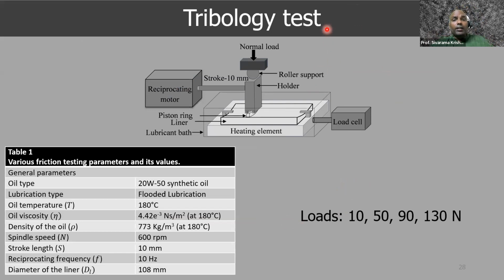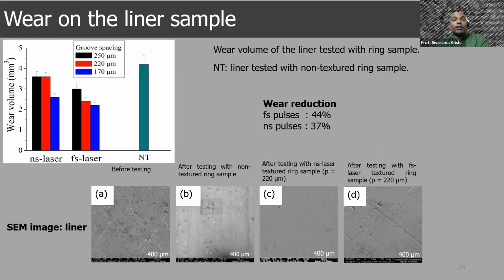So we used a reciprocating motor to measure the tribological properties at various different loads, all the way from 10 to 130 Newton. We used the same oil in both cases, for nanosecond as well as femtosecond laser pulse grooved or microstructured samples, and we studied the tribological properties. That's the work of Maran. And here is a very typical result which we found.